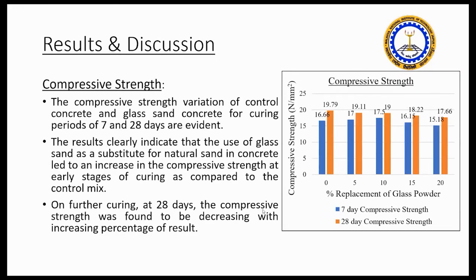This is the compressive strength. The compressive strength variation of control concrete and glass concrete for curing periods of 7 and 28 days is evident. The results clearly indicate that the use of glass sand as a substitute for natural sand in concrete led to an increase of compressive strength at early stages of curing compared to the control mix. At 0% it's 16.66 Newton per mm square, whereas it is 17.5 at 5 and 10% replacement level.